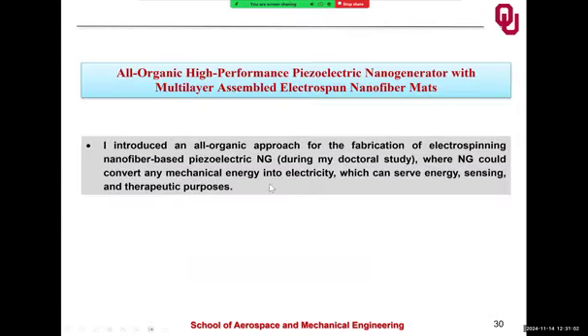One of the works I want to highlight, a very important work that I did during my PhD, is that with these nanofibers, one of the problems is making the electrode, because those fibers are air permeable, so there is porosity. So any kind of deposition technique may not be feasible to make the electrode. So I came up with an all-organic approach for the fabrication of a nanogenerator out of that nanofiber.